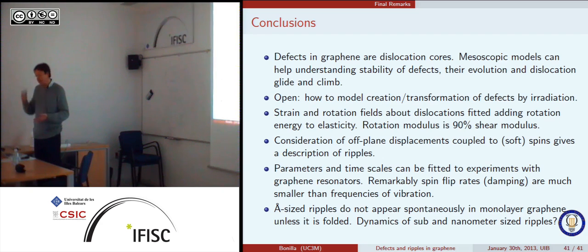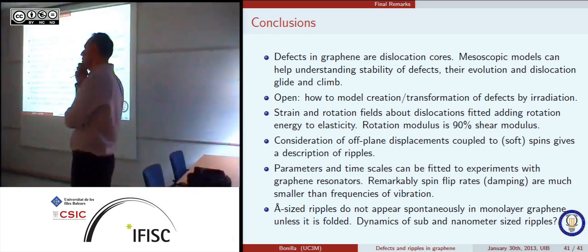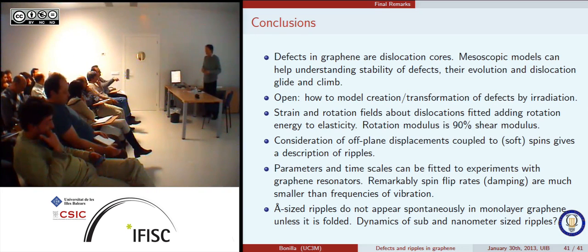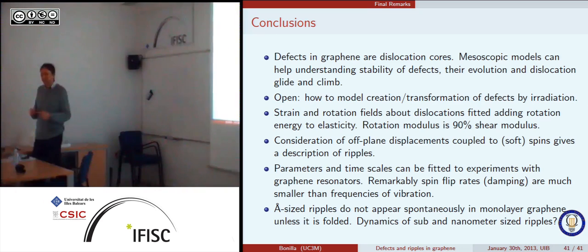So this thing is important in suspended graphene because there the ripples are having an intrinsic life and they are not following the substrate. And also, does it matter the way this graphene sheet is pinned at the borders of this hole? Well, the holes are big enough so that the ripples are minute in comparison. So it's believed that they are an intrinsic effect and they do not care that much about what happens so far from them. You need to pin them because, as I said, the graphene will crumple immediately and try to form just a ball or something.